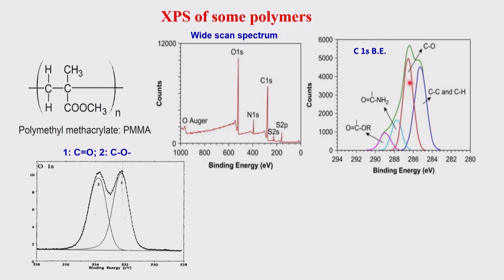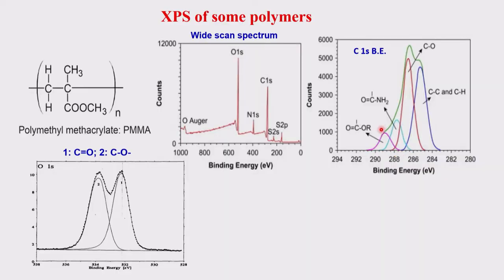The pink or red peak corresponds to C-O with some NH2 type groups. You can also examine the ratio of these peaks to work out the polymer composition at the surface. You cannot get the molecular formula from this, but you can see what is at the surface. The lower binding energy corresponds to carbon with one single-bond oxygen, while higher binding energy corresponds to double-bonded or multiple oxygens.